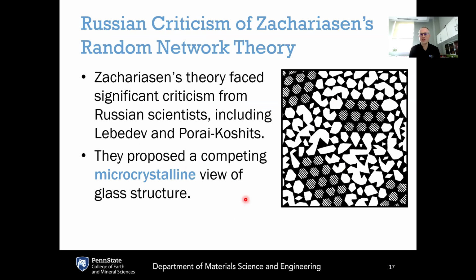And this debate actually goes back many decades before then. The biggest criticism of Zachariasen's random network theory actually came out of the Soviet Union by some Russian scientists. And they had proposed what's called a microcrystalline view of glass structure. The microcrystalline view said that the glass is not completely disordered, but it is composed of really tiny crystals that are in some sort of a disordered matrix. So there's a disordered matrix phase, but within it, there are these really tiny crystals, and these crystals are too small to be observed from X-ray diffraction, and that's why XRD doesn't show